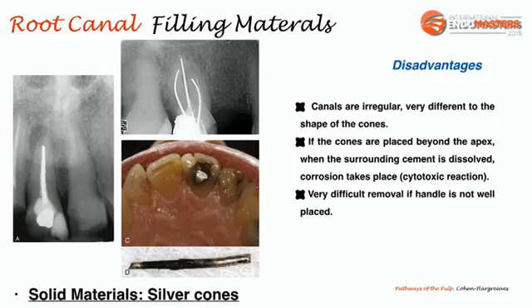There is easier manipulation and less need for canal enlargement. However, this led quickly to the misuse of the material, and silver cones rapidly started to be associated with numerous treatment failures. Among the disadvantages of the material, we can mention that the canals are very irregular and very different from the shape of the cones. If the cones are placed beyond the apex, when the surrounding cement is dissolved, corrosion takes place and it becomes a very cytotoxic material. And last but not least, the material is very difficult to remove if the handle is not well placed or it's broken when the clinician is trying to remove the cone.